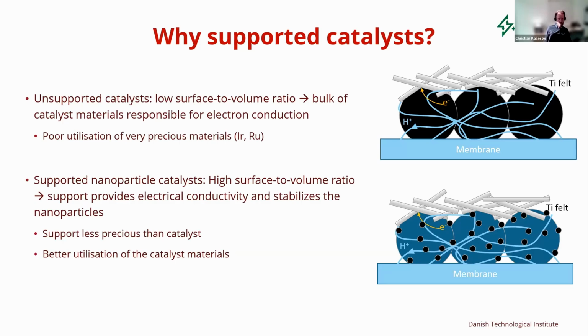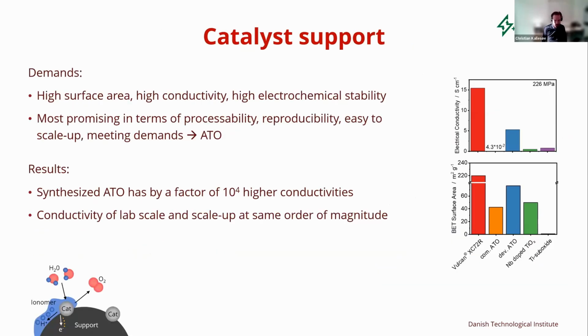And that brings us to the catalyst support, which was done in cooperation with Fraunhofer Institute in Germany. We need a support structure that has a high surface area, high conductivity, and also a high electrochemical stability. And the last part here is also why we cannot use carbon structures, simply because they corrode under these PEM operating conditions. What we found is that the most promising materials, both in terms of these three demands, but also in terms of reproducibility and how to scale it up, is antimony doped tin oxide.